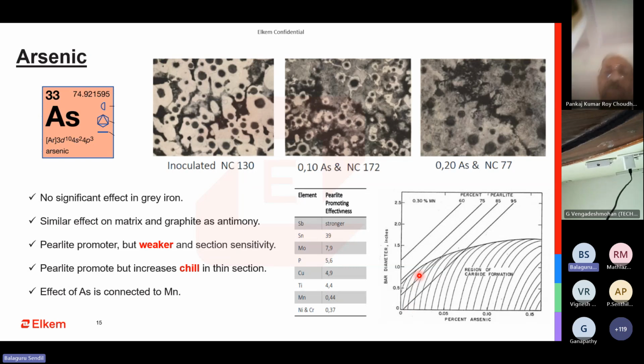So you have to correlate this to the amount of manganese that is going to be present to neutralize this. You cannot have high manganese and high arsenic. Or you can think that my manganese is under control, but I'm still getting an issue of pearlite, an issue of chill. Then we try to see whether the arsenic content has increased or not. So this is arsenic. The next one is titanium. This is very, very important.